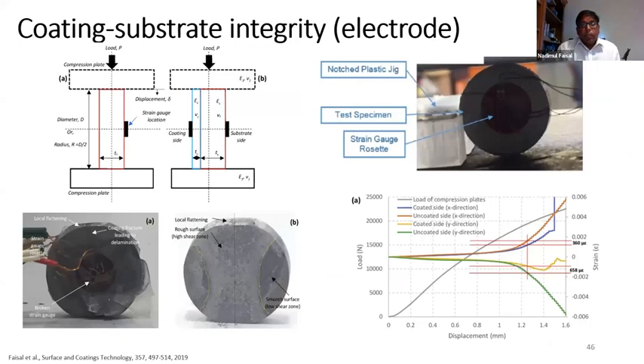Now we need to have a very strong, structurally integral electrode. So this is one technique which we used. We have a high strength alloy, Hastelloy, and we did a coating on one side and compressed along this direction. And we put on strain gauges, and we wanted to know at what load it will fail. By putting on a strain gauge, we were able to identify how strong these catalysts can be using the technique we deployed. So that was destructive testing.